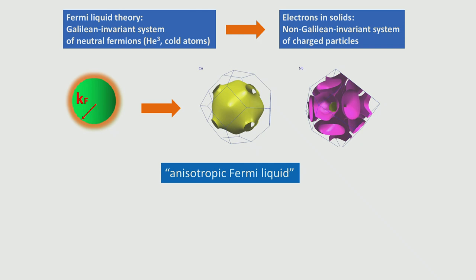Of course, the original theory of Fermi liquid was developed for a Galilean invariant system with isotropic interactions and neutral particles, while in condensed matter we deal with electrons in solids - and they're also charged. So we have to make a mental jump from a system with an isotropic Fermi surface harboring neutral fermions, to a system where the Fermi surface can look like this - this is copper - or even like this - this is niobium - and at the same time we need to take into account long-range Coulomb forces. This procedure has never been done rigorously. What we have is something known under the name of anisotropic Fermi liquid: it is a belief that if we morph our Fermi surface in this particular way and keep the Coulomb interaction, the physics will not change much. And by and large, this is true. But here are the pitfalls I mentioned before, and I will walk you through them.